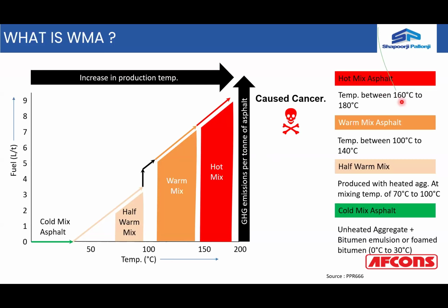definition part: the hot mix is generally in the range of 160 to 180 in Indian conditions, but it goes beyond 180 overseas, especially when you refer to the French codes. And the warm mix temperature is 30 degrees lower than your hot mix temperature. In this particular case, you can go from 30 to 35. So you can range your warm mix temperature from 100 to 135 or 140 max, but not above 140, because if you go above 140, your compaction temperature requirement, which is close to 120 or less than 120, will make it difficult to roll.